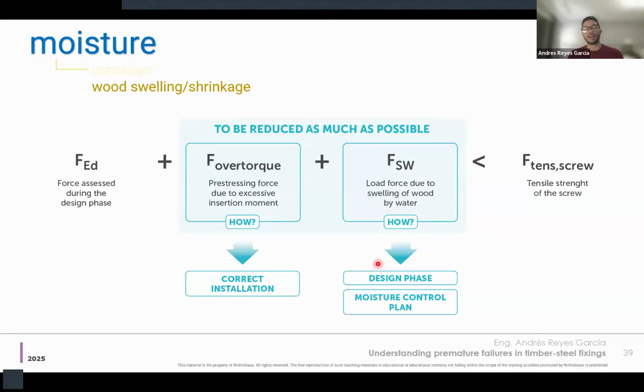That would mean that, well, this is a bit of an exaggeration, so take it for what it is. But right now, as designers, we consider the force during the design phase needs to be below the tensile capacity of the screw. So this is very, very rough. There are two factors that we're definitely not considering, which is the over torque force and the swelling force. All three of them should be lower than the tensile capacity for the design to achieve the design life. But they need to be handled differently.